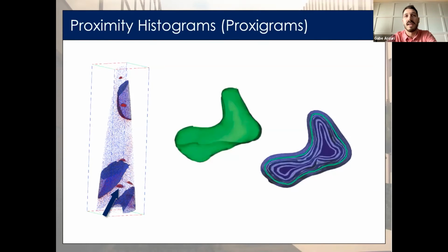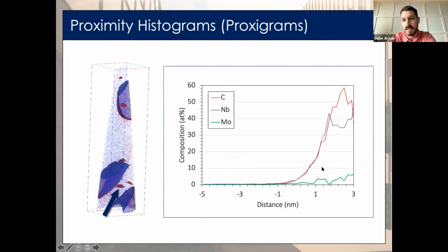Using a defined isosurface, the local atomic neighborhood adjacent to the interface is examined. Atomic positions are correlated with respect to their distance to the normal of the isosurface and used to generate a histogram measuring the population of atoms in a series of shells, which you can see here, at increasing distances from the position of the isosurface. With this, a concentration distribution profile for any species can be generated.